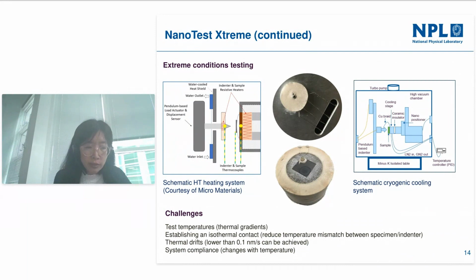And for both systems, there are challenges. First is the temperature mismatch or thermal gradient between where the sample surface is and the thermocouple location. And the same for the indenter side, we couldn't put the thermocouple close enough to the indenter tip. The second challenge is to establish the isothermal contact, which would lead to thermal drift, and the last one is the system compliance of both systems.